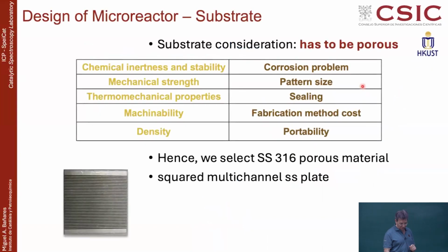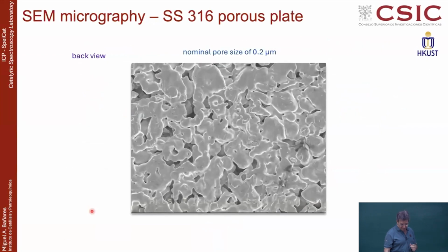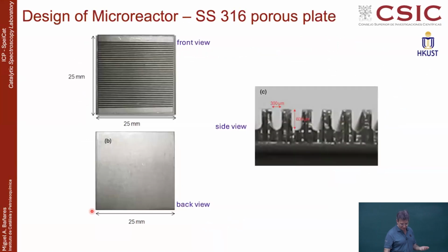with these microreactors. This microreactor is the size of a stamp. It's very small. It's a micro reactor. You can put it in your pocket. You can put many in your pocket because they are tiny things. And it's just stainless steel with a very big porosity, 0.2 microns. 0.2 microns is very big porosity. The glycerol carbonate, the ammonia, everything will go through it. So this is too big a porosity, but this is just a preparation of a porous substrate to make something special.